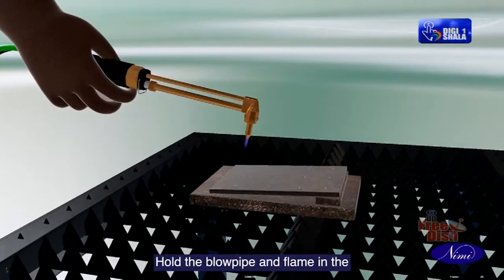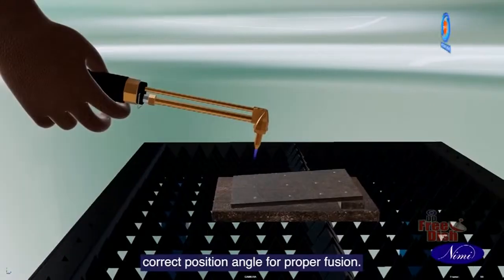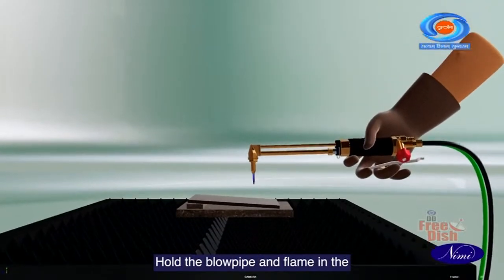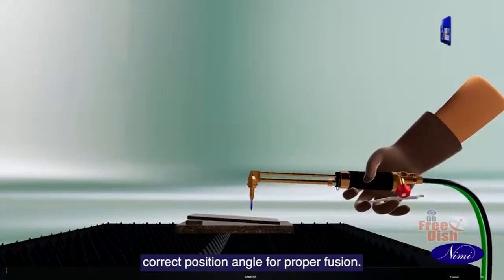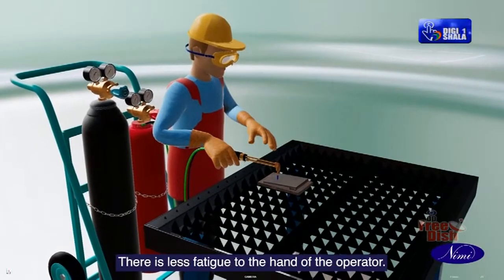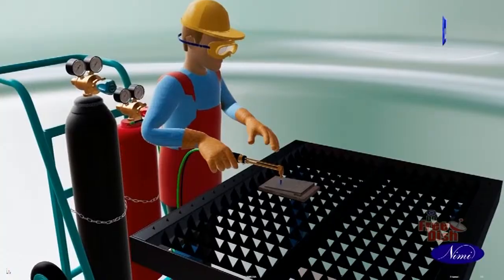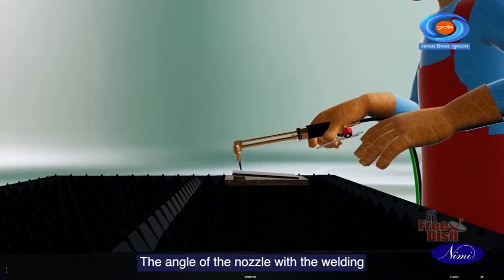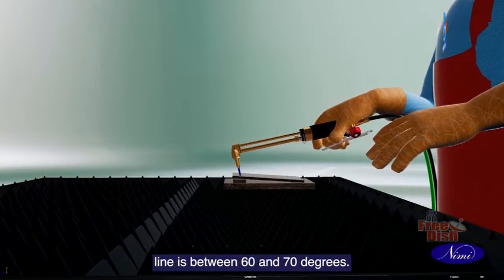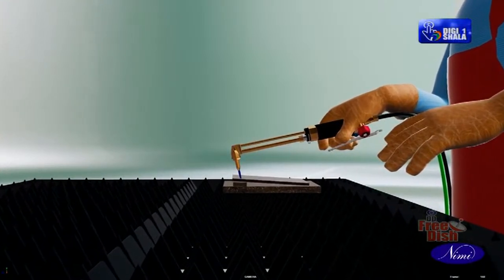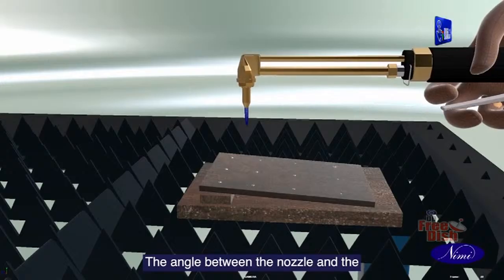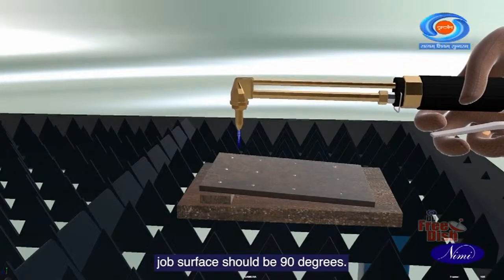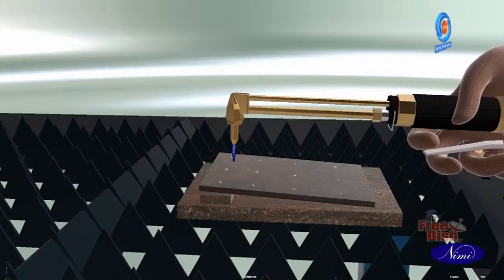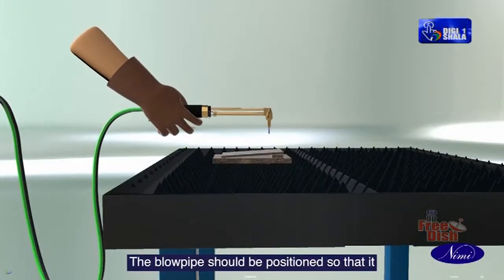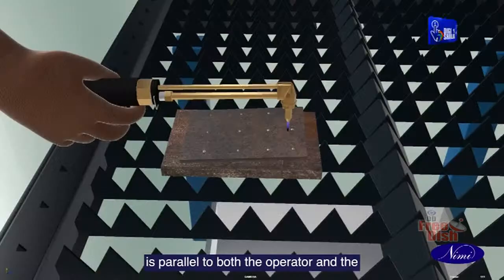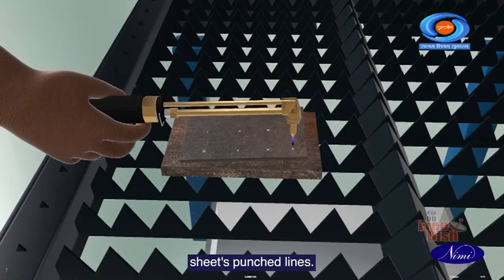Hold the blowpipe and flame in the correct position and angle for proper fusion. There is less fatigue to the hand of the operator. The angle of the nozzle with the welding line is between 60 and 70 degrees. The angle between the nozzle and the job surface should be 90 degrees. The blowpipe should be positioned so that it is parallel to both the operator and the sheet's punched lines.